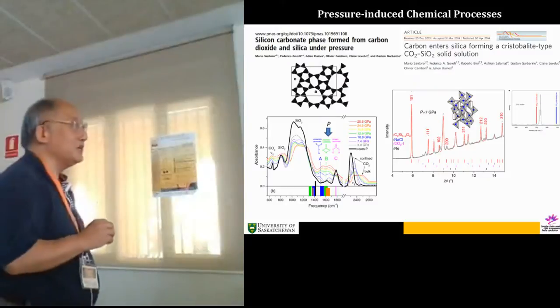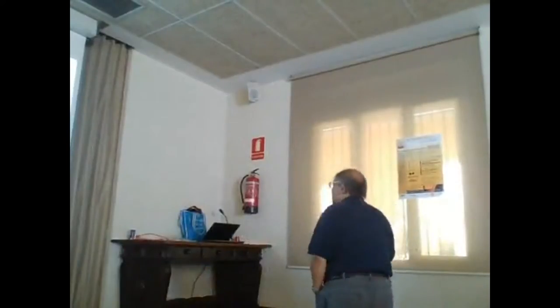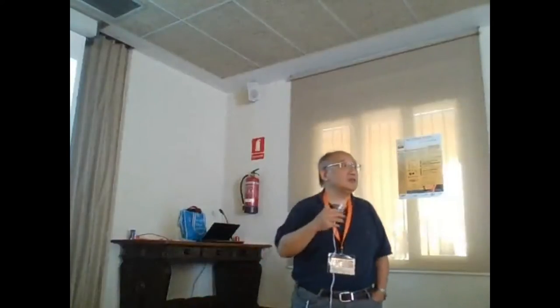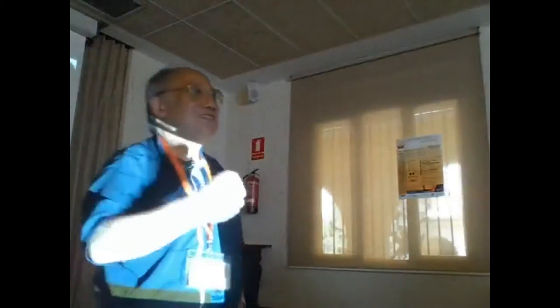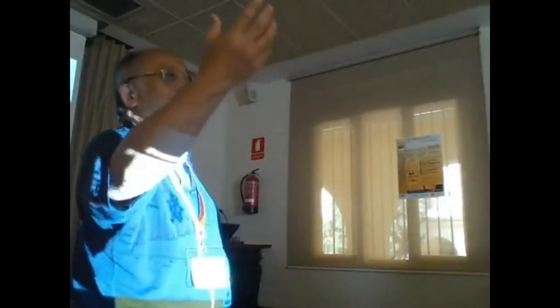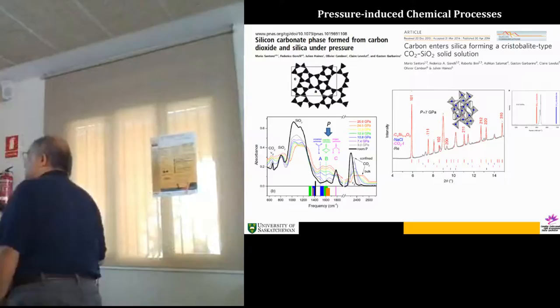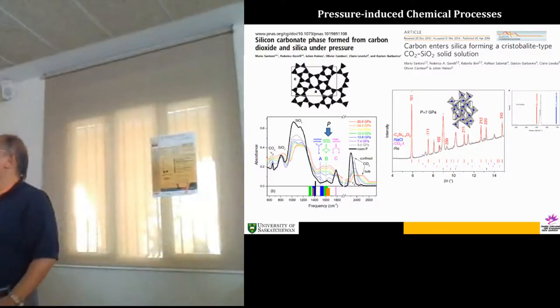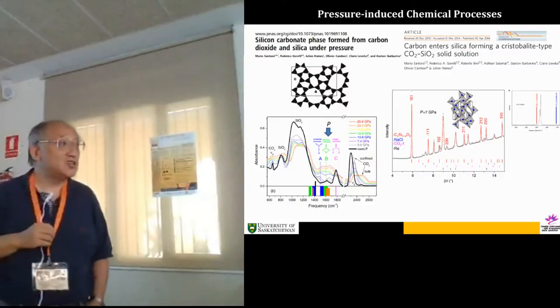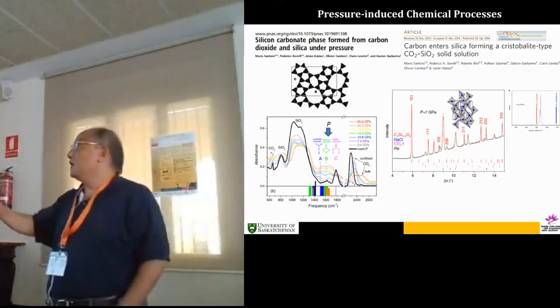Another thing that really amazed me was also the chemistry by the Italian group, excellent piece of work. They load CO2 in SiO2 for a particular reason, because I heard earlier today that there's a lot of CO2 in the lower mantle. I think Hans said that. So that's a reason. When you have CO2, you have silicate, you have some temperature, you have the pressure, what do you get? And they did the first experiment. They put the CO2 in a zeolite, fill it up, and then heat it up. And they can see formation of different linkage of the SiO bond.